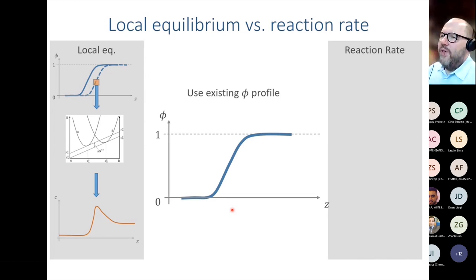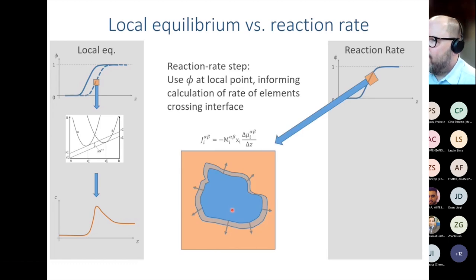In our reaction rate model, we do this slightly differently. We use our existing order parameter profile phi. For each point in that profile, we can then use the magnitude of the order parameter and the magnitude of its gradient to evaluate the migration of atoms or species across the interface. So we simulate the growth and the change in composition. And this is what I'd like to call the reaction rate step.